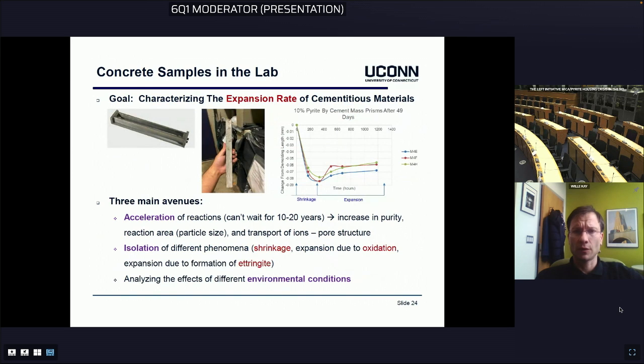I only have 3 slides left. We mix and cast our own concrete in the lab so that we have samples under controlled conditions and we know exactly what we put in there. The goal is to measure the expansion rate at accelerated conditions. You see here mortar bars, similar to what Benoit mentioned with the expansion of those mortar bars. On the right side you see some preliminary data where the mortar bars shrink, and if they have a high concentration of reactive metal sulfides, the shrinkage behavior is reduced or even turns around into an expansion behavior, which is indicative of oxidation or secondary mineral development.